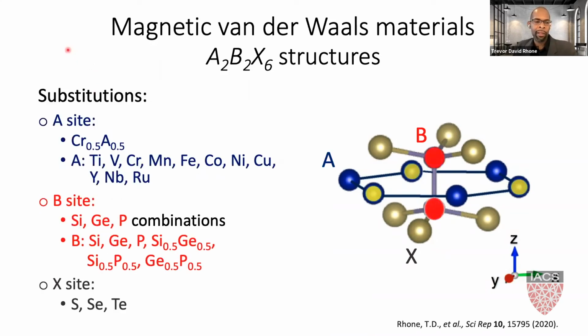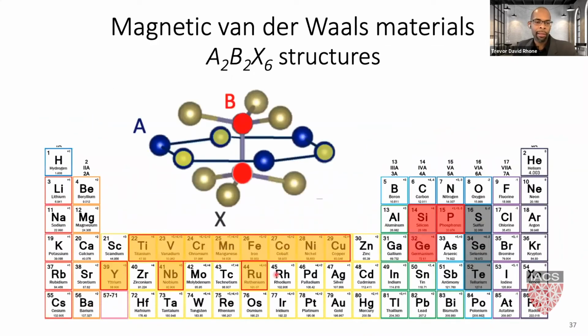To make clear the atomic substitutions, essentially every other A site was chosen from the list of transition metals. The B sites were combinations of silicon, germanium, and phosphorus, and the X sites, above and below the plane, were either tellurium, selenium, or sulfur. In the periodic table, they're shown here: A site substitutions in this part, the B sites here, and the X sites here. From these first principles calculations, we can get the magnetic moment, which parameterizes how strongly magnetic these materials are, or their magnetization.